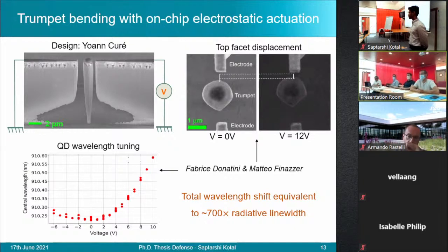Predominantly, that's the reason. So I think coupling strengths don't change. But then the fact that we're emitting much faster, the time scale for the coupling to act on the machine is shorter. So if I take the absolute height of the side peaks, do they decrease or do they stay the same and the main peak increases? No. So basically, what we lose from the main peak's intensity, amplitude, we create the two side peaks. So actually, if we increase the amplitude of the zero phonon, it's going to decrease. Okay, that is clear. Okay, that's very clear.